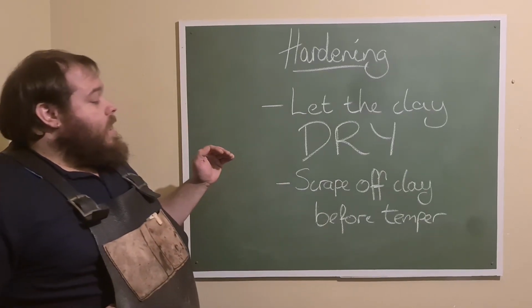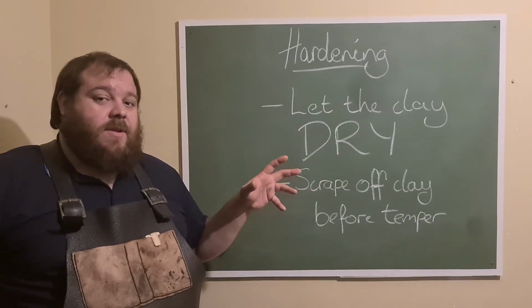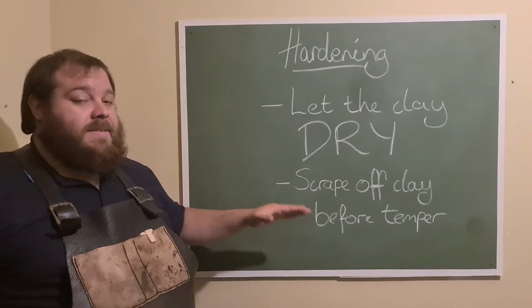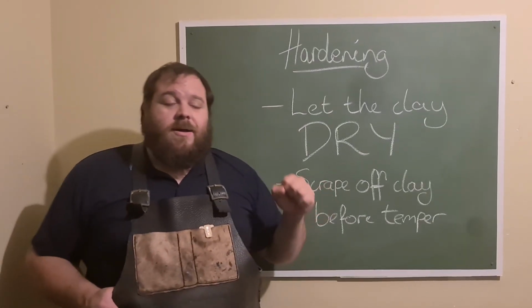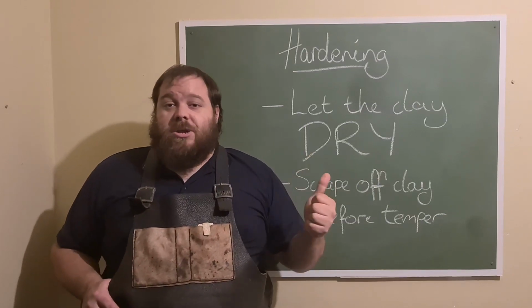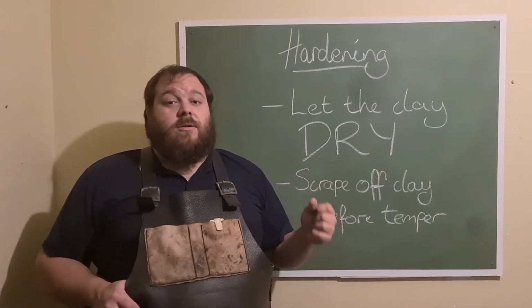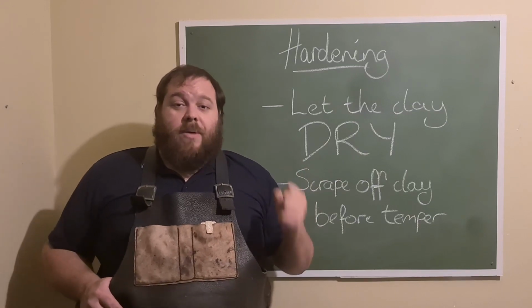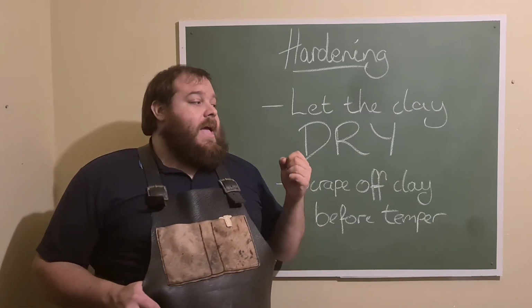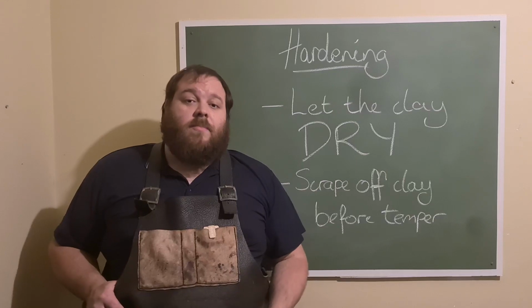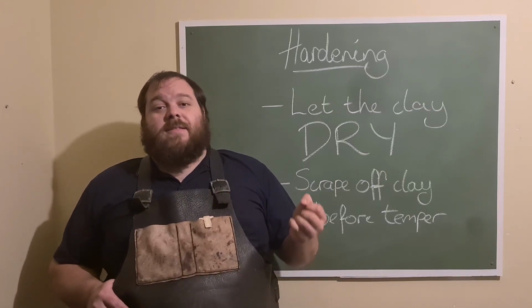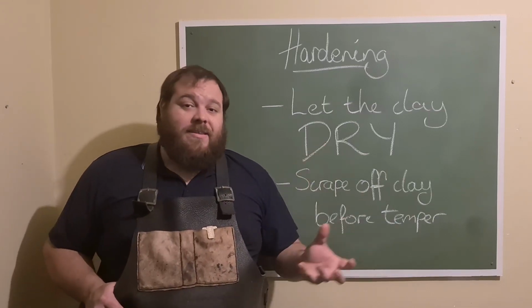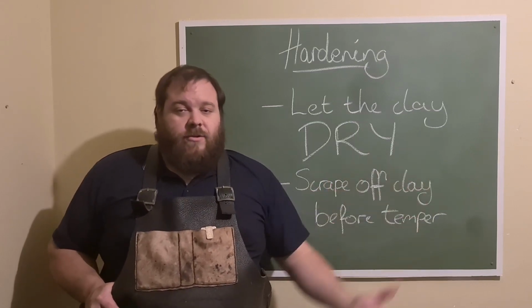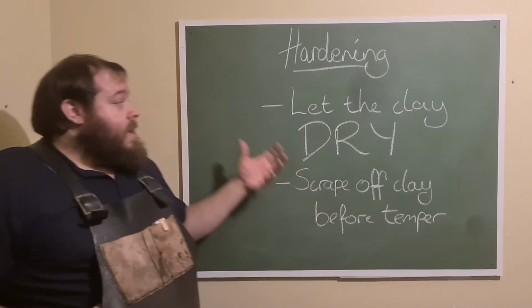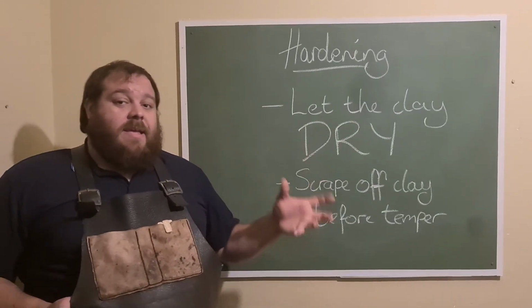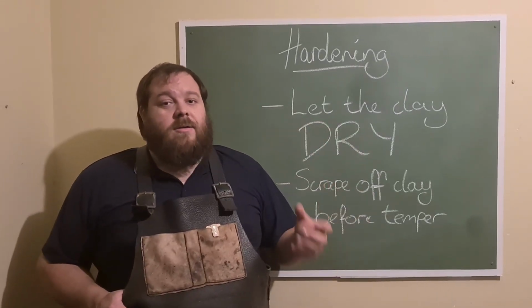But if you do have a successful Hamon quench and the clay is still on there, please scrape it off before you temper. There are a couple of reasons for this. A, if you're quenching in oil, the clay will hang on to that oil like it's thirsty for it, and it will burn and it will stink and it'll be horrible. And also it creates extra thermal mass, and the problem with that is that it means that the temper may not actually find the depth it needs if you don't use like a full 2-hour cycle. So basically, hardening is as simple as anything else. You just have to be a little bit more aware of the clay.